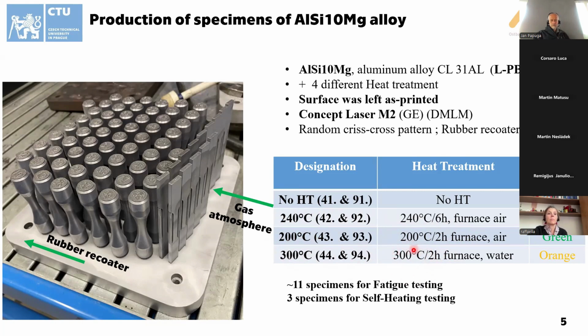What is interesting and a slightly novel approach for the heat treatment is the T300. It's heating up to 300 degrees Celsius for 2 hours and then water quenched. However, it's unique in the sense of this powder, but the EOS printing manufacturer and powder manufacturer recommends this heat treatment for their powder, so it's not that uncommon.